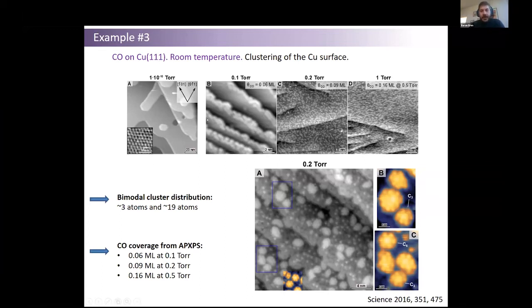And what you see here is an image in ultra high vacuum conditions, which has been imaged hundreds of times before me. You see these large terraces separated by monatomic steps, large meaning that the terraces are hundreds of nanometers squared. And if you zoom in, you can atomically resolve them, of course, because we have an STM. But now we see that in the presence of gases, let's say in the Torr pressure range, something is covering the surface, and as we increase the pressure, whatever is covering the surface is increasing in size and density. And if you go to 100 Torr, then the entire surface is covered with these structures.